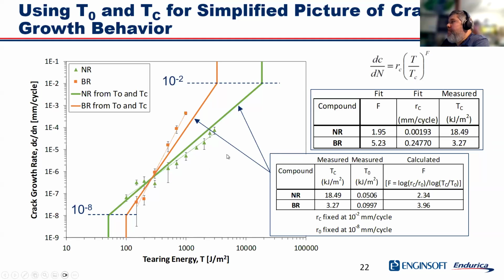And here's an example of the calculation, right? So if you give me TC and T naught, I can just use this equation right here, F equals log RC over R naught, which in this case is going to be 10 to the minus 2 divided by 10 to the minus 8, divided by log TC over T naught. And that gives you an estimate of your power law slope. And so you can see here for the NR, the actual experiment gives us 1.95. Our approximate method gives us 2.3. For the BR, we see 5.2. And for the approximate method, we see about 3.9, or so about 4.0.